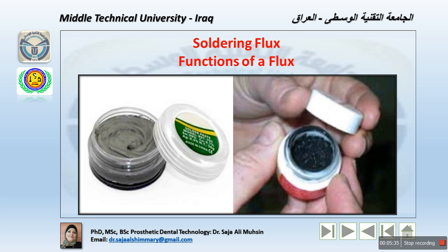The composition of the flux is generally borax glass, about 55%, boric acid, about 35%, and silica, 10%. A borax type of flux is used when gold alloys are soldered, while a fluoride type of flux is used when cobalt chromium alloys are soldered. This is related to the composition of the material of the flux itself. Now we also have anti-flux. The anti-flux is used to control the flow of the solder. The flux is placed on the parts that we want to join, but the anti-flux is placed on the parts that we don't want the metal to go through or adhere to.